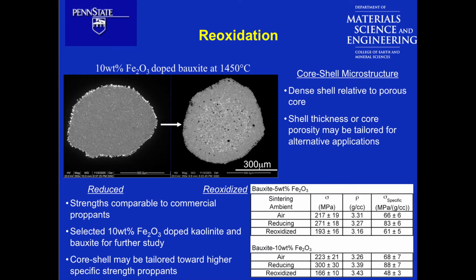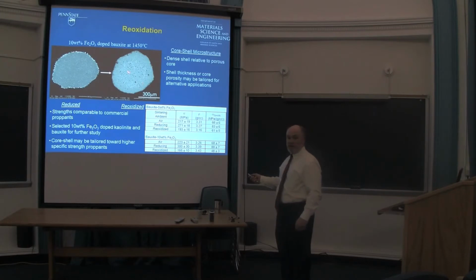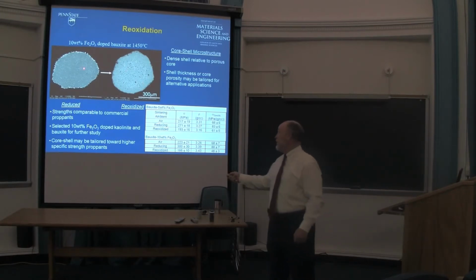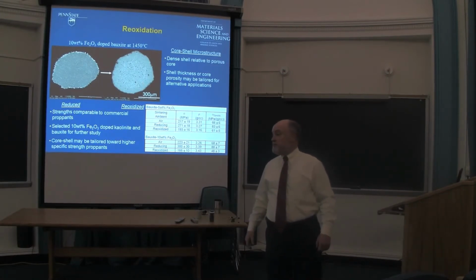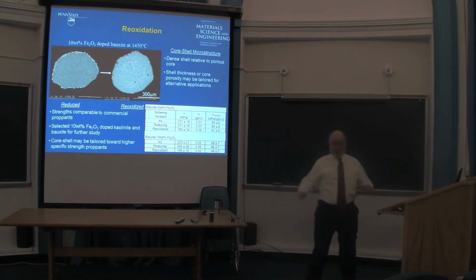And going from the dense, metallic, decorated surface with heat treatments in air, we can turn an outer rind into an iron-containing aluminosilicate while at the same time having entrapped iron, metallic iron, Fe, zero valent, in the interior, which, for those of you skilled in the art of mechanical properties of ceramics, is a ductile phase toughening agent. Fracture toughness of that material will be significantly higher than that material. Okay? These are the things we manipulate.